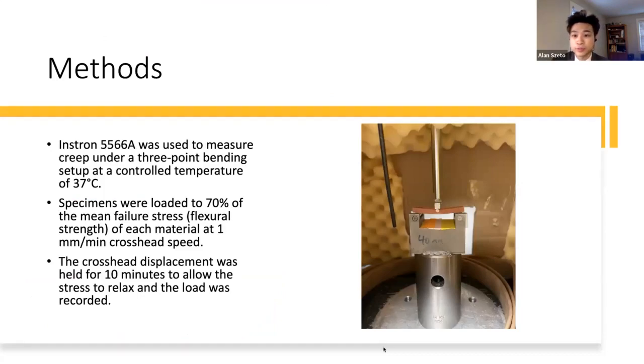And then after the specimens were prepared, a universal mechanical tester, Instron 5566A, with environmental control box was used to measure under a 3-point bending setup at a temperature of 37 degrees Celsius plus or minus 2. The specimens were loaded to 70% of the mean failure stress of each specimen at 1 millimeter per minute crosshead speed, and the crosshead displacement was held for 10 minutes to allow the stress to relax, and the load was recorded. And here is a picture of how the Instron machine is putting stress on the specimen.